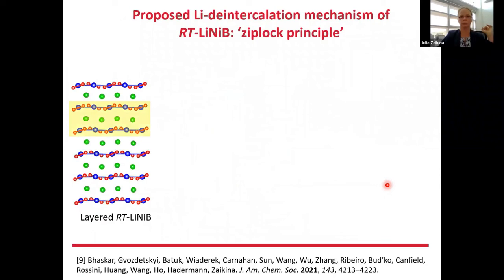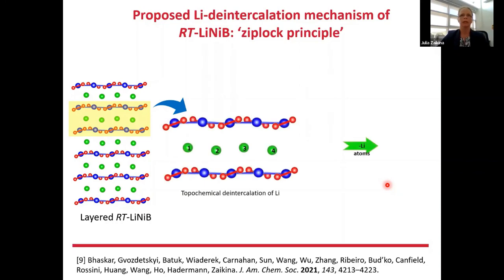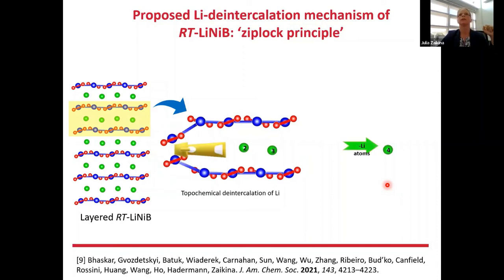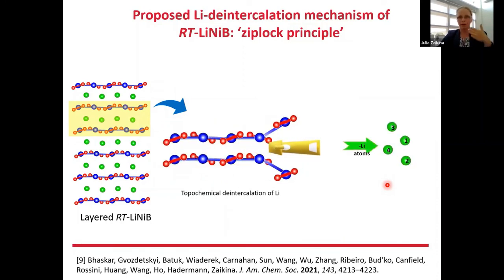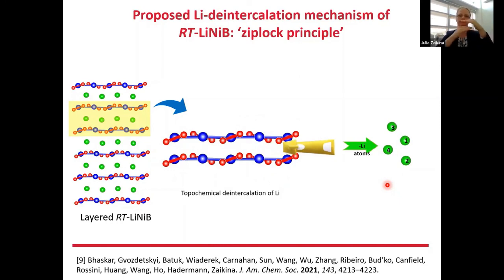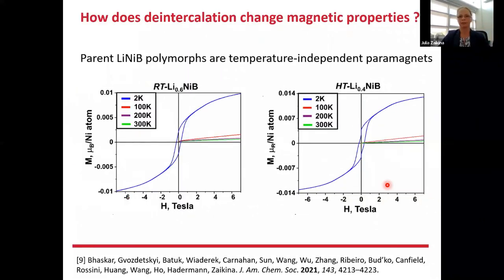And so by using those methods, we determine the deintercalation process, which we call the Ziploc principle. So when 2 nickel-boron layers have a lithium sandwich in between, the lithium atoms come out to form lithium oxide, and then the Ziploc closes to form that nickel-boron layer substructure with the 2 nickel-boron layers. And to wrap it up, I want to say that the parent compounds are temperature independent paramagnets,